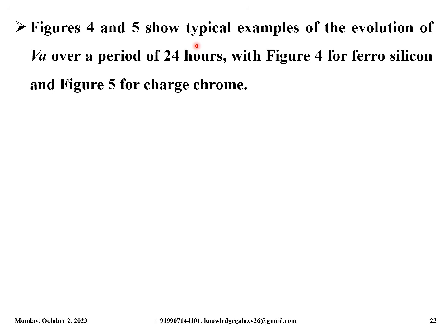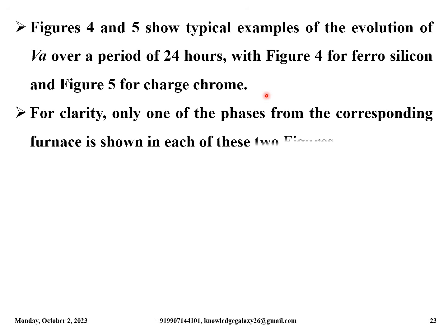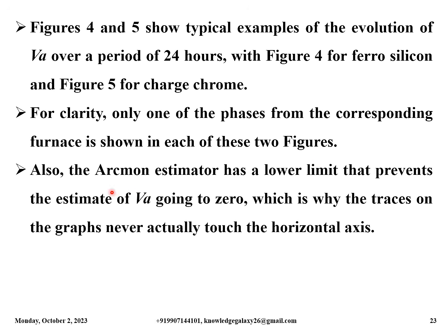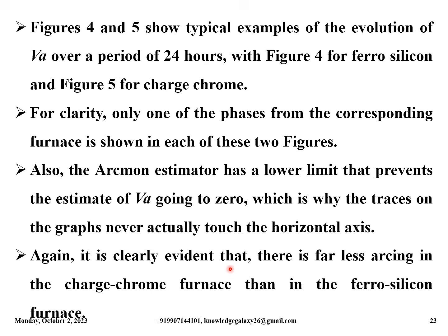Figures 4 and 5 show typical examples of the evolution of VA over a period of 24 hours, with figure 4 for ferrosilicon and figure 5 for charge chrome, which are described in the coming slides. For clarity, only one of the phases from the corresponding furnace is shown in each of these two figures. Also, the ArcMon estimator has a lower limit that prevents the estimate of VA going to zero, which is why the traces on the graphs never actually touch the horizontal axis. Again, it is clearly evident that there is far less arcing in the charge chrome furnace than in the ferrosilicon furnace.